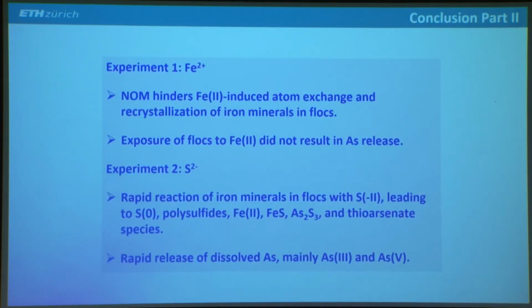So in conclusion, in these experiments, we found that the natural organic matter actually hindered iron-2-induced atom exchange and recrystallization of these iron oxides, which is a very well-known process for pure iron minerals like pure ferrihydrite. But in these floc samples, it doesn't seem to occur. And as a result of that, exposure of the flocs to iron-2 did not result in arsenic release.